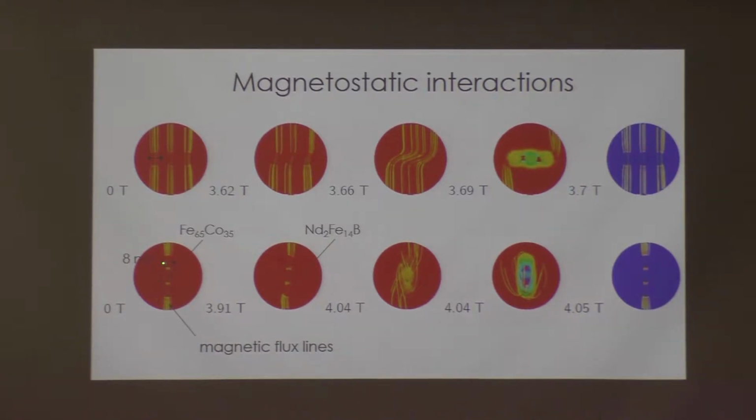This flux concentration stabilizes the magnetization, and we need a much higher field in order to reverse it. So if we have the opportunity, in designing a magnet, to put our soft magnetic inclusions at certain places, it would be good to use these chains and not this horizontal arrangement, because here we concentrate the flux and we improve the coercive field.